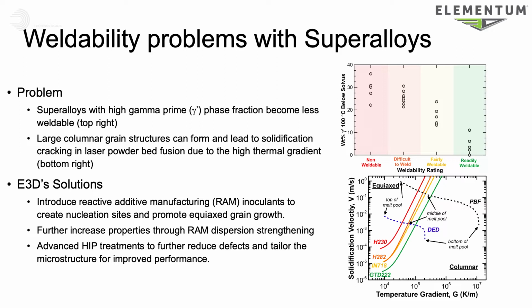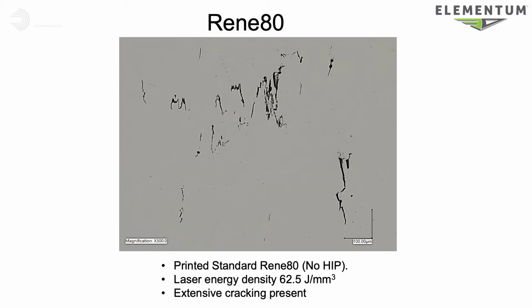One of the biggest factors in the weldability of the material is the fraction of the gamma prime phase content. As you increase in gamma prime phase, the weldability generally drops. Weldability tends to be very applicable to the printability. So a material that has poor weldability is going to have poor printability with laser powder bed fusion as well. So the issue is you try and print these very desirable materials and you get significant cracking throughout the microstructure, and the properties of course suffer.